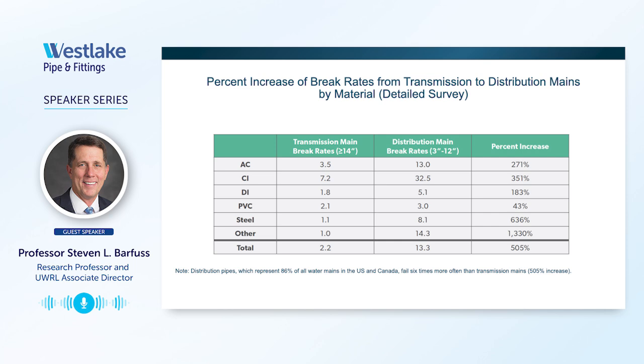This is a table that we broke out transmission pipe sizes greater than 14 inch and distribution pipe sizes 3 to 12 inch in terms of these common pipe materials and their break rates. And you can immediately see the overall break rate of 2.2 right here for transmission sizes, 13.3 for distribution sizes, and a 505% increase, which is 6 times difference between these two sizes. There's a couple indications of something that's happening here. Obviously, if you're managing a transmission line, you're going to take really good care to install it, to maintain it, to inspect it. It's your cash register for the whole system. When that goes down, the whole system goes down, right?